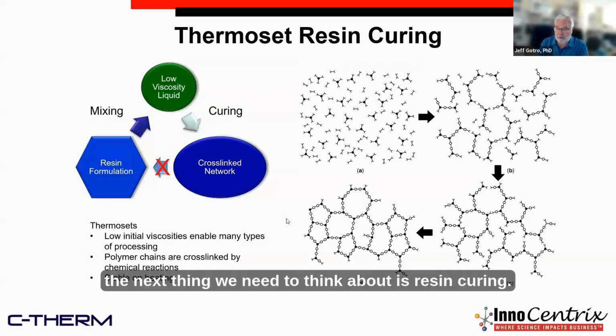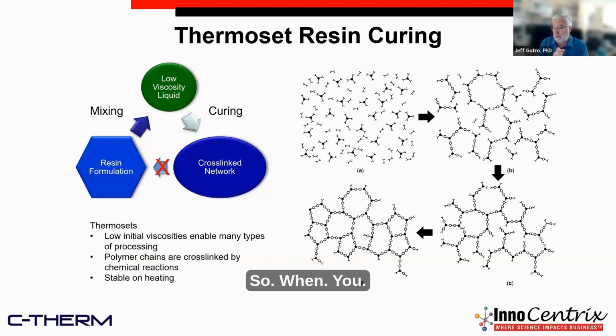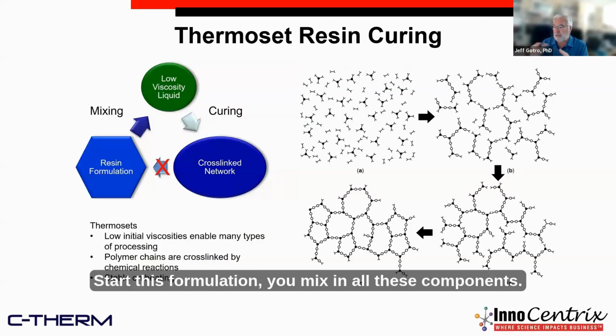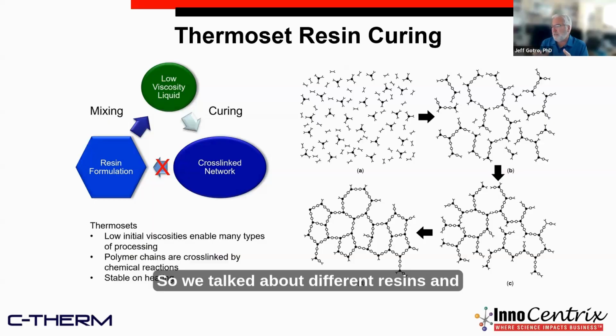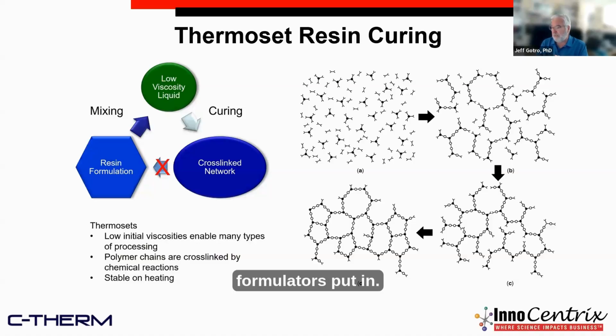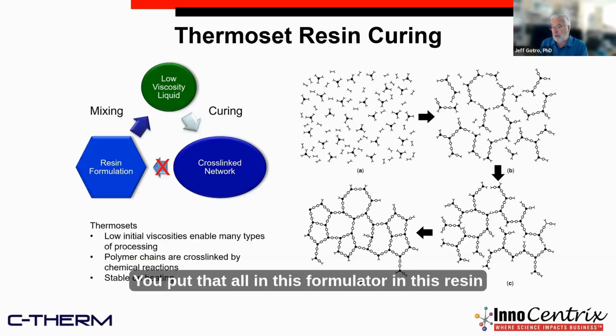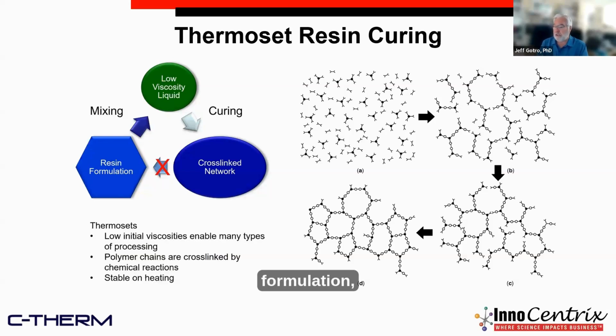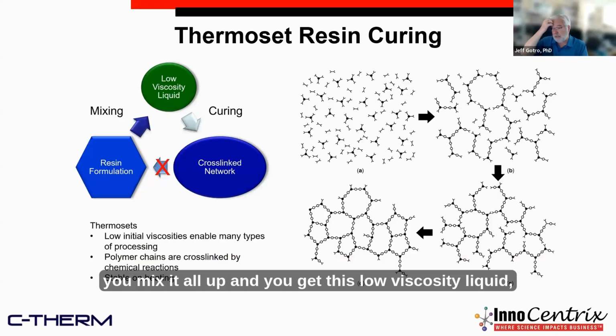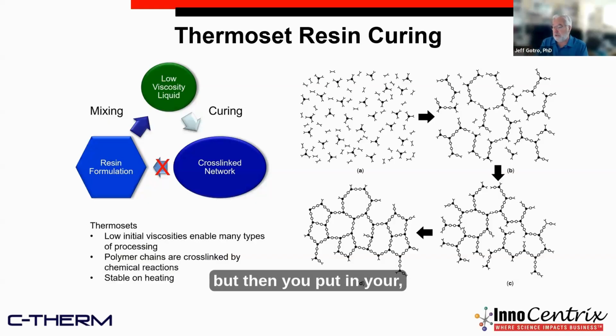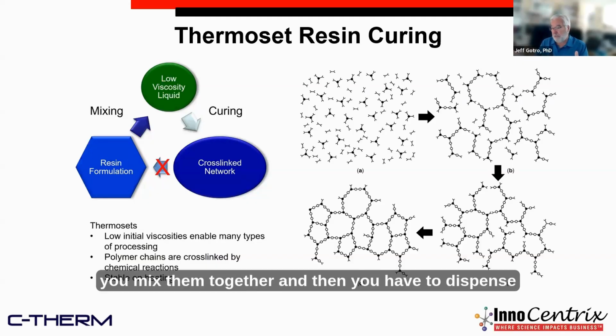Now, the next thing we need to think about is resin curing. When you start this formulation, you mix in all these components. We talked about different resins, and we didn't really talk about hardeners, adhesion promoters, wetting agents, and other additives that the formulators put in. You put all that in this resin formulation, you mix it all up, and you get this low viscosity liquid. But then you put in your fillers and mix them together, and then you have to dispense them.